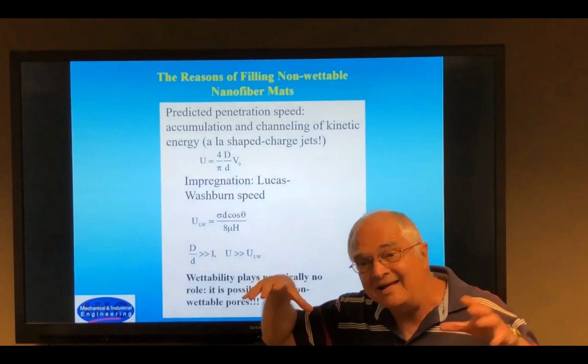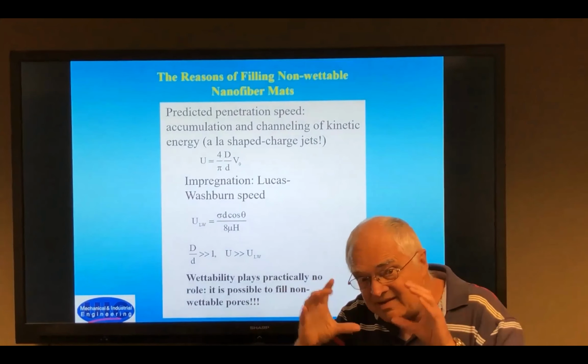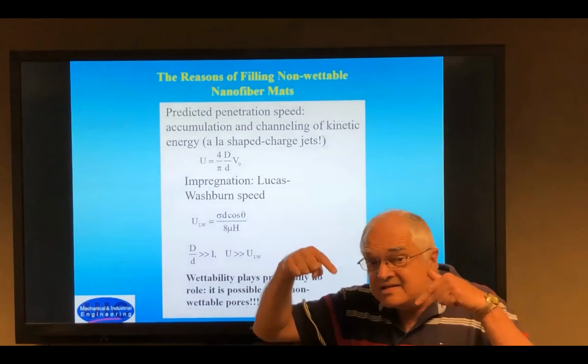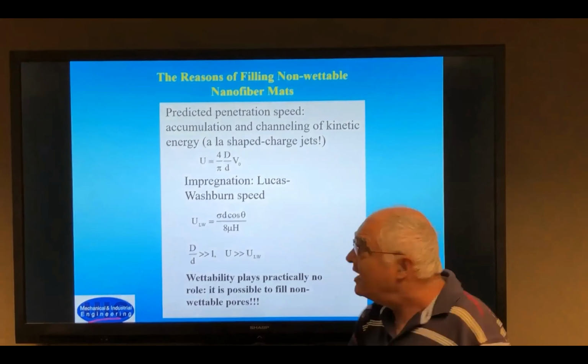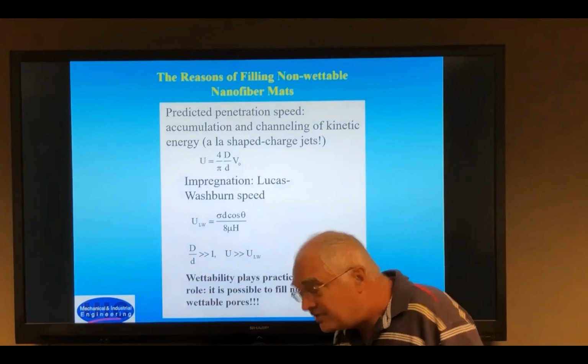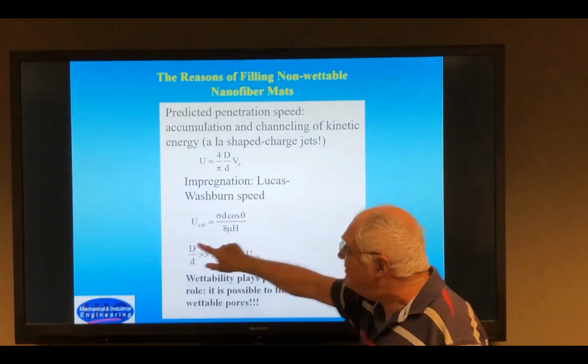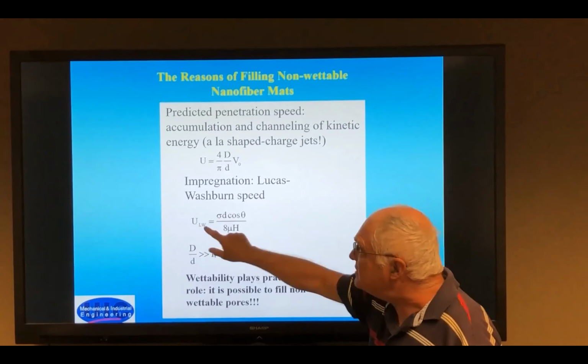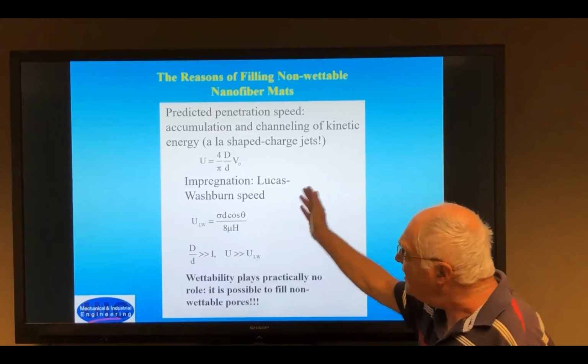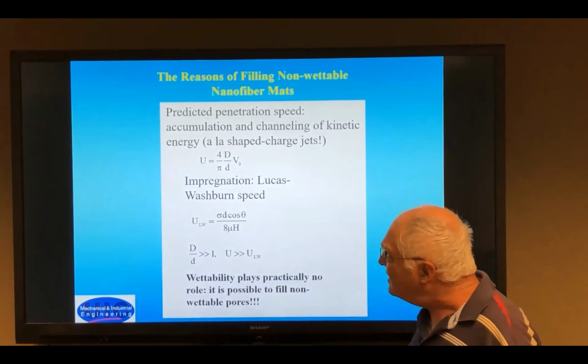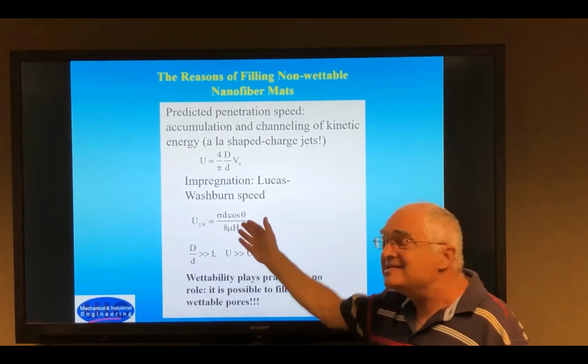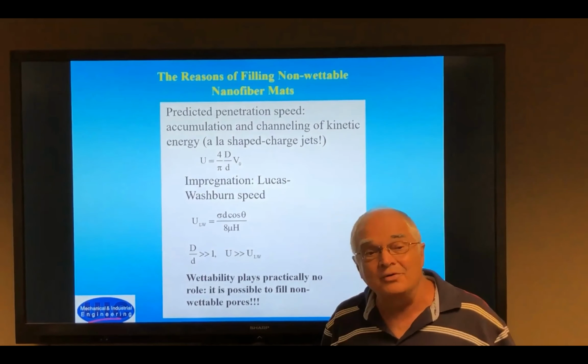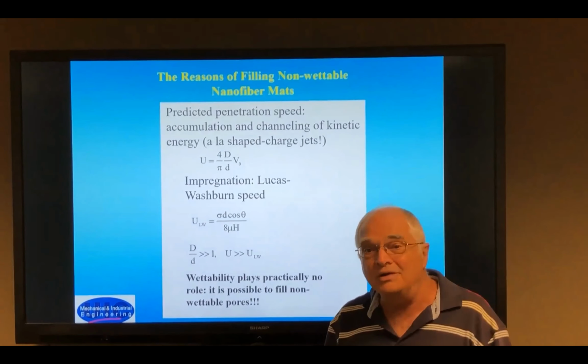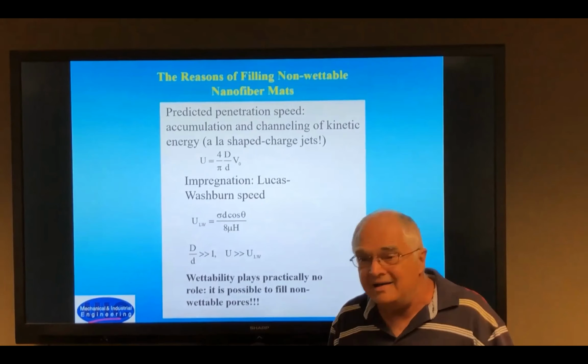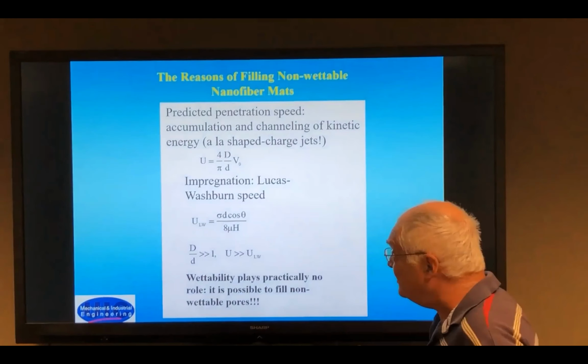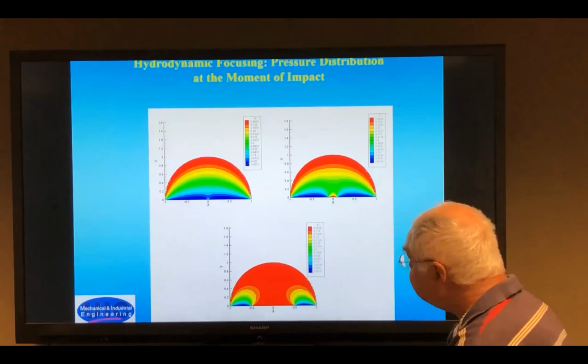It means that the kinetic energy coming with this big droplet is channeled into a very small pore. As a result, the penetration velocity is so high that whatever wettability-related velocity is predicted by the Lucas-Washburn formula doesn't matter. Therefore, you can essentially deliver water into Teflon, any superhydrophobic material. That's exactly what happens. Please, the next slide.